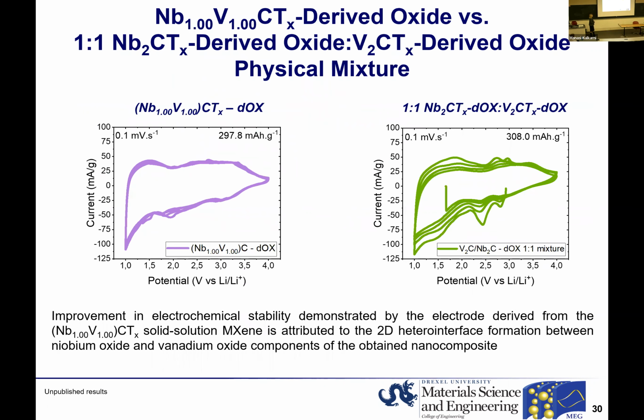And one last thing I wanted to show you on this topic is that, just out of curiosity, we compared the electrochemical performance of the solid solution MXene derived oxide with the 1-to-1 niobium to vanadium ratio with the physical mixture of the materials, prepared again through the vanadium carbide and niobium carbide transformation into oxides. And we see that the MXene derived composite shows much better stability compared to the physical mixture, which to me says that there are some advantages in forming a heterointerface. When the solid solution precursor is used, the heterointerface between vanadium oxide and niobium oxide nanoparticles can stabilize the structure of the final composite much better compared to simply physically mixing the two materials. So we are also exploring this role of the heterointerface further.